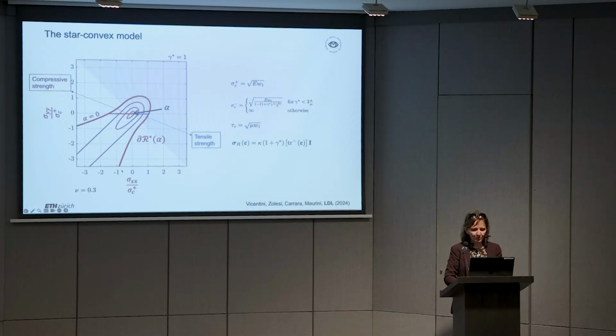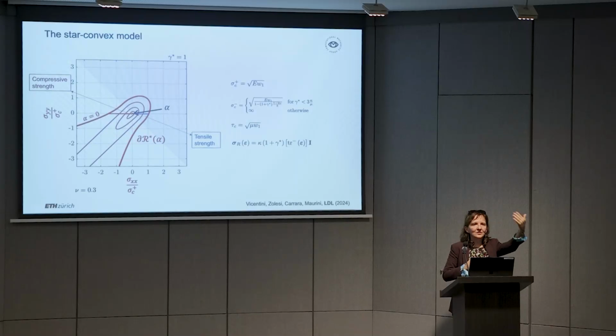But at least with this new decomposition, our purpose was not actually to have a realistic strength surface. Our purpose was to be able to control the tensile strength and the compressive strength independently. So if you have a case where points in tension and points in compression will be competing for nucleation, then you can use this model because this model will allow you to set the compressive strength to a realistic value independently from the tensile strength, and so you can really have a realistic behavior in the competition among tension and compression, and at the same time the residual stress is of the good type.